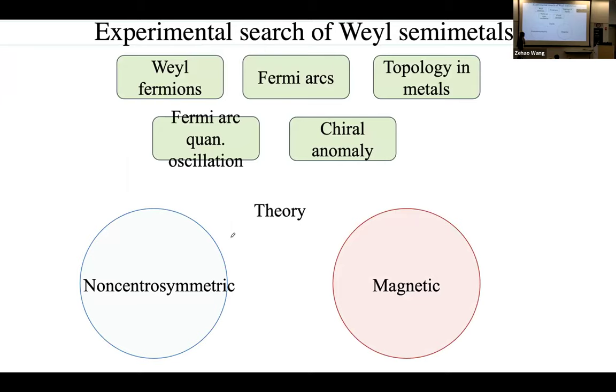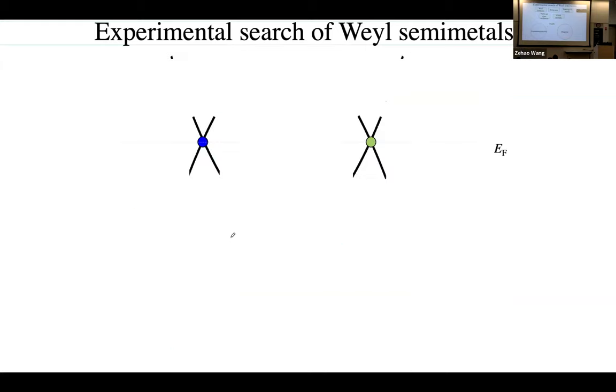The theoretical discovery of Weyl semimetals was made in 2011. People were already excited about topological insulators, and now there was a chance to realize topology in metals, with interesting phenomena including Fermi arc quantum oscillations and the chiral anomaly that Anton discussed. To have a Weyl semimetal, you need to break either inversion or time-reversal symmetry — corresponding to non-centrosymmetric or magnetically ordered materials. Despite interesting proposals such as pyrochlore iridates and topological insulator multilayers, these were either difficult to grow or turned out to be strongly correlated.